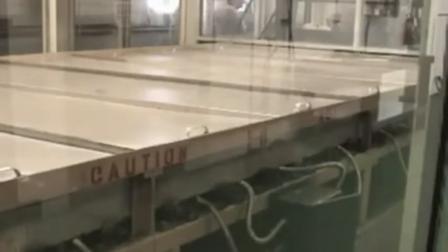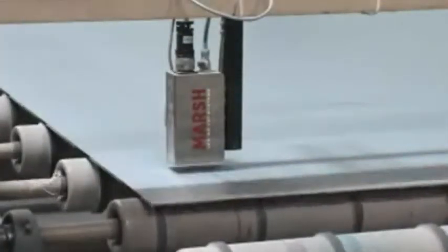After the application of the protective layer, the mirror is moved into the final oven section. The mirror cures in the ovens as it continues down the line. Heated to a temperature of between 265 and 285 degrees Fahrenheit, the mirror takes approximately 6 minutes to move through the ovens and be properly cured. Once out of the ovens, the mirror back is labeled automatically by date and time of manufacture.